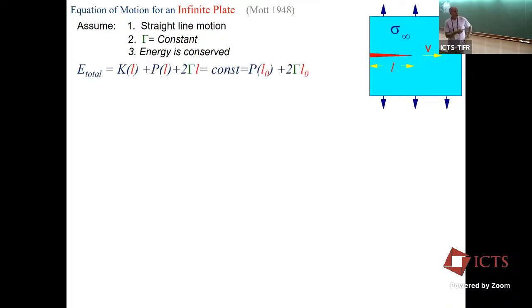Okay, so the total energy is just equal to the kinetic energy, which is dependent on the instantaneous length L of the crack, and also its instantaneous velocity V. The potential energy for a given crack length L, now you're creating 2 new surfaces here. So if gamma is defined as the energy per unit surface that we're creating, so the total energy is 2 times the fracture energy times the length of the crack.